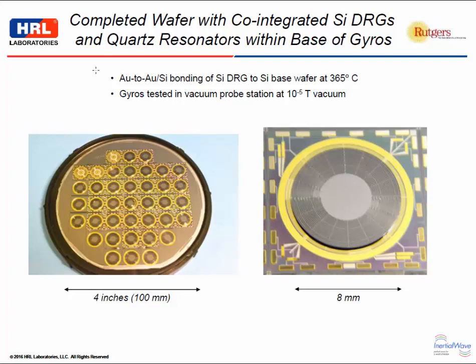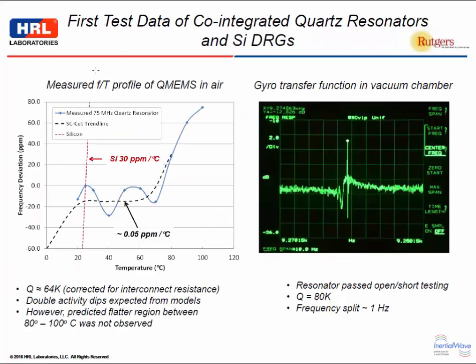post. So again, we did the silicon bonding, gold-to-gold bonding at around 365, and then we tested the gyros in a vacuum probe station that we had with a probe card for the gyros at about a 10 to the minus 5 torr vacuum. We tested the quartz devices on a hot plate or on a hot chuck with Cascade Microtech probes in air.